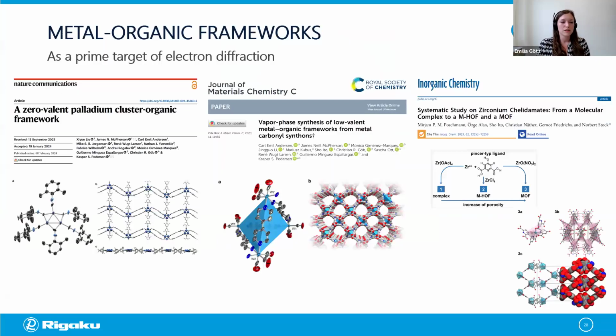So let's first have a look at the MOF structures, or at least the ones I haven't talked about already. Electron diffraction is usually pretty beneficial for MOF structure solution because we don't need large crystals to be grown. We can also drop cast the crystals directly from the mother liquor and cryo plunge them before inserting them into the cryo transfer holder so that the possibility of a solvent loss is minimized. And this way, the Synergy-ED was able to help many scientists in solving their MOF structures.